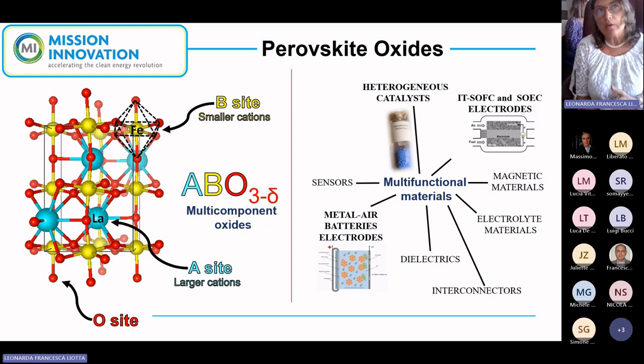In order to use a convenient material in the electrocatalytic cathodes, we selected a class of materials that is very well known, perovskite oxides. Perovskite oxides have the main structure ABO3, where A is the A site and is usually occupied by larger cations, like for example lanthanum, and B sites are occupied by smaller cations, like for example iron, and are